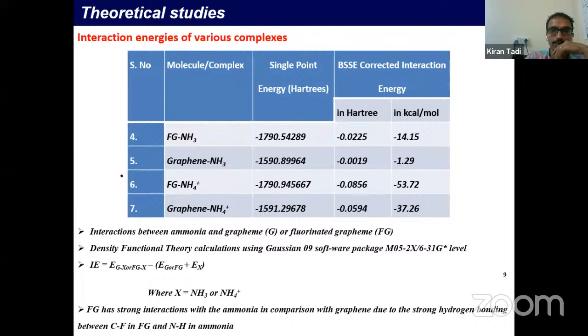So I did some optimization results here, and in the case of this fluorinated graphene, you can see the fluorinated graphene has the highest stabilization energy, interaction energy here, and as well as if you see the fluorinated graphene and ammonium ion.